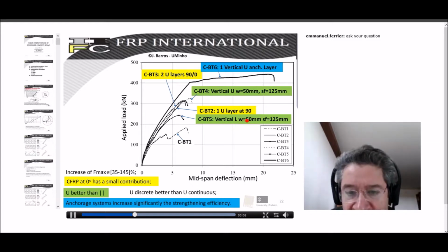Another aspect is when we compare the beam that has vertical strips of wet layup system, formed by strips of 50 millimeters width and spaced at 125, to the one composed of the same type of strips but placed laterally, on the lateral surfaces. We realize that the U configuration is much more effective in terms of shear strengthening than the one where we applied the FRP systems on the lateral faces. So this is a very important aspect.